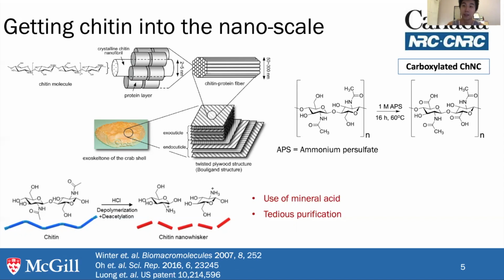In collaboration with the National Research Council of Canada, the NRC, they've been able to make these chitin nanocrystals, or CHNCs, using a mild oxidant in the form of ammonium persulfate. You can see here it uses the oxidant to cleave and depolymerize this polymer, as well as oxidize this C6 hydroxyl group into a carboxyl functional group. So it's a carboxylated chitin nanocrystal.